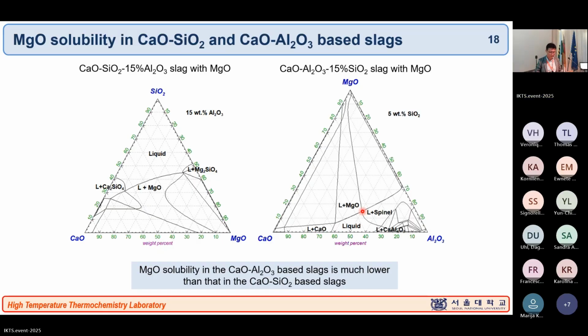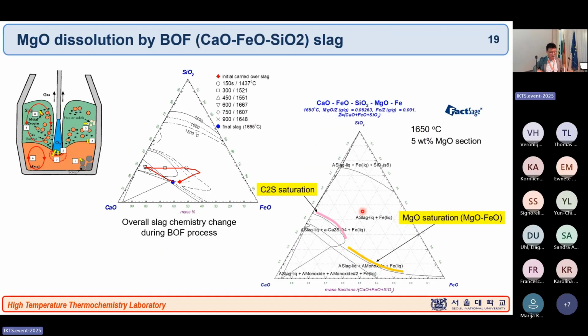Okay, and now let's move on to the MgO dissolution in the CaO-FeO-SiO2 slag, the so-called BOF, the basic oxygen furnace. So this BOF is a very important process in steelmaking. You have a high amount of carbon in the steel produced from the blast furnace, about 4%. So we want to reduce the carbon content. So we are injecting oxygen, and while we are injecting the oxygen, carbon is going away as CO gas, but iron starts burning as FeO. So the composition of the slag in this furnace is changing from this point all the way traveling back to this point again, the same composition.